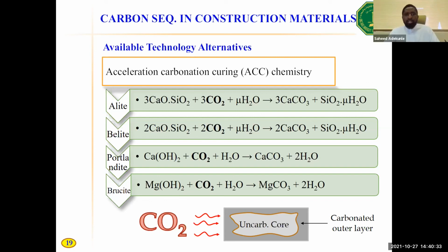Thank you. Yeah, you're right, Professor. Thank you so much for this issue. At the early stage of ACC application, people thought that the solution for complete carbonation of concrete members is to use FRP, okay? But after the discovery of the simple fact that you can still maintain your alkalinity even after you apply ACC, then we are at liberty to either use steel bars or FRP. Don't forget, FRP can only work in tension, not in compression. Still, in the compressive zones of structural members, you still have to use something different from FRP. And that is why it is interesting to note that it is possible to maintain the alkalinity of concrete, even if you do deep penetration of CO2.